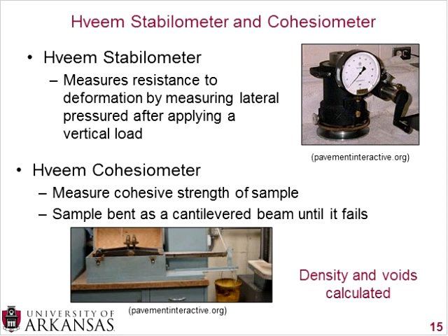I've never done this before. But if you look at this place I'm circling here, the sample goes inside that, and it's actually split down here in the middle, so along this dotted line I'm putting in. The sample is on one set of steel plates on the right side, one set on the left side, but it can actually rotate. And you fill a bucket over at the end of this lever with material, and that essentially causes the lever to try and move down, and you split the sample along the dotted line.